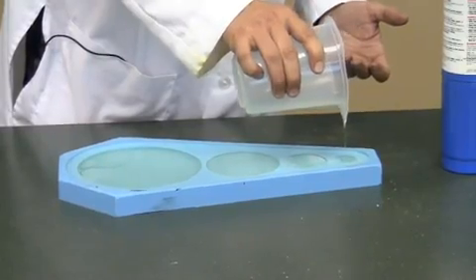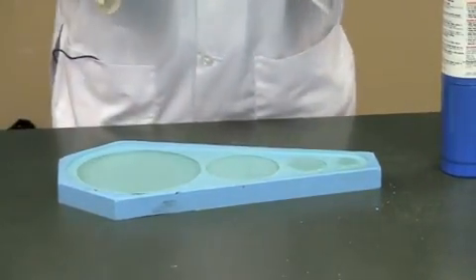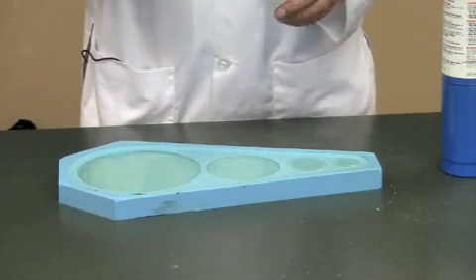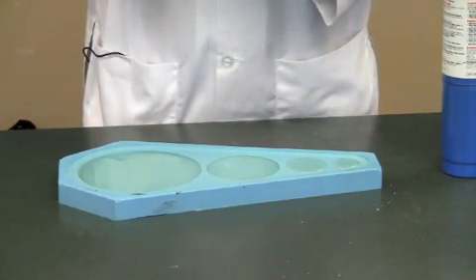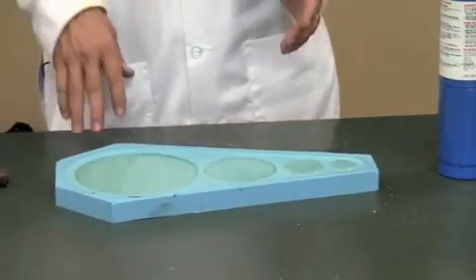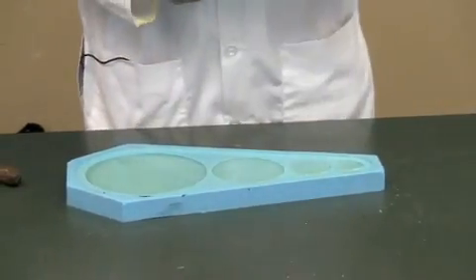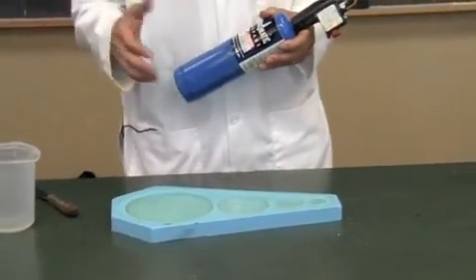Just give it enough time so it flows out nice and evenly. And if you have some trapped bubbles, you should take maybe like a metallic wire or a metal spatula, not wood, to tickle any of the air that is trying to hold itself against the side or bottom of the container. And then finally, when the air rises up, if it doesn't pop on its own, a small propane torch works great. What you want to do is you don't want to burn the polymer. You just want to warm the air above it.